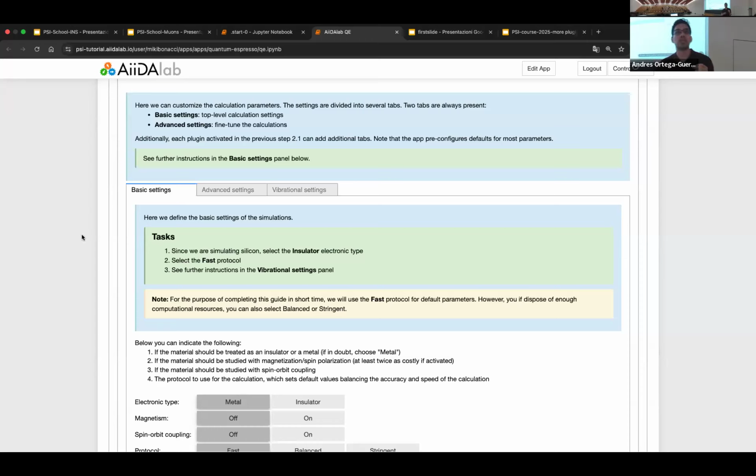So it is important that you address the electronic properties, in the sense that maybe you need a DFT plus U to open the bandgap. That is a known problem. Or you should know that it has a relatively sufficient bandgap, because you will be applying an electric field for purposes of computing the polarizability response. And it is important that the system has a bandgap. How small? Maybe you're wondering, maybe even up to 0.3, because I work with graphene nanoribbons, and even at that small, it behaves relatively well.